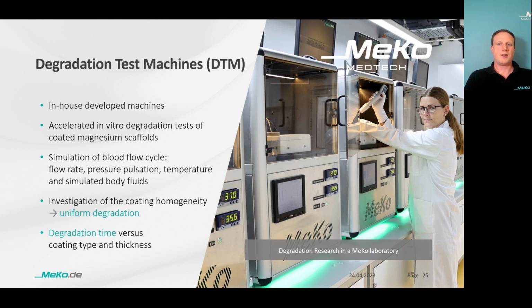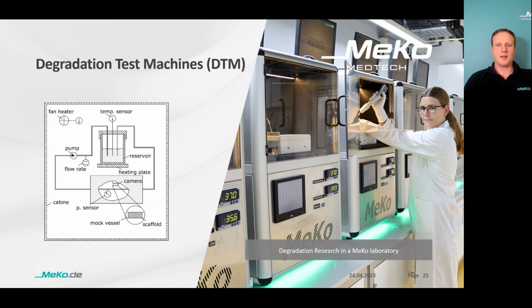To test the degradation kinetics of magnesium-based scaffolds, MeKo developed their own degradation test machines. These are comparative tests in pulsatile simulated body fluids to investigate degradation homogeneity depending on coating type and thickness. And here you will see a principal setup of the degradation test machine. A peristaltic pump pumps the SBF, so simulated body fluid, through the mock vessel where a stent or scaffold is placed.